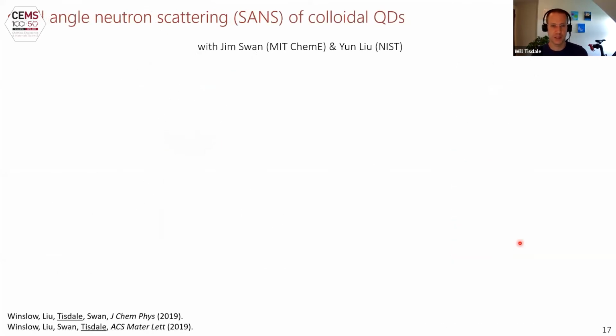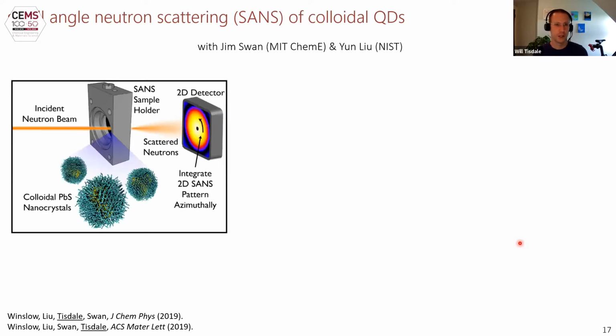We have begun to be very interested in the surfaces of these nanocrystals. The size and shape of the cores is something that we can understand well from electron microscopy or from X-ray diffraction. But it has historically been very difficult to understand what is on the surface of these nanocrystals because of lack of good characterization techniques. Recently, Jim Swan, who's another associate professor in the chemistry department at MIT, and I have been working together trying to use small angle neutron scattering to learn more about the surface ligand layers coating nanocrystals.